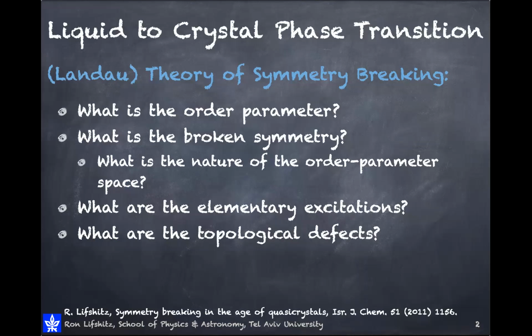Through the phase transition, as we change some external parameter like a temperature or a pressure, this uniform phase, which has all translational and rotational symmetries, a continuous group of symmetry operations, goes through the phase transition and the structure evolves, the crystal crystallizes, and then one loses some of these symmetry operations.